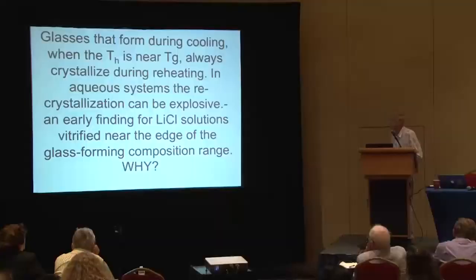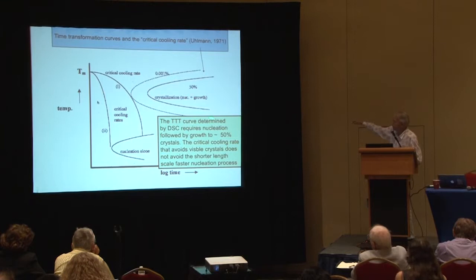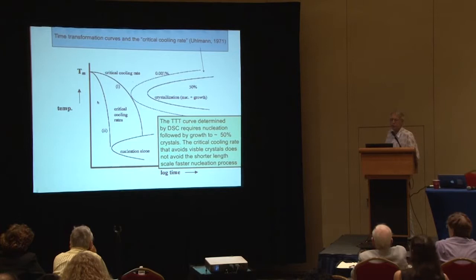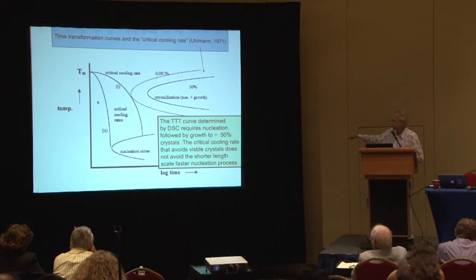where we recognize that what we were determining here was this combination of nucleation and growth, and yet the nucleation process itself, involving very tiny particles and very small length scales, is intrinsically faster and occurs with its maximum probability at a much lower temperature. Now, people in the glass business have talked about this for quite some time, but quantifying it has been more difficult. And just a simple adaptation of the isothermal calorimetry method allows us to make this separation.